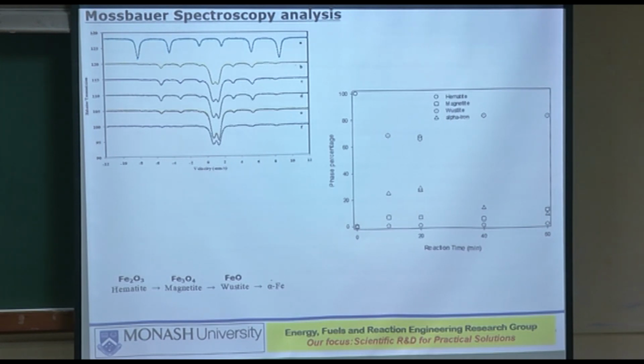You determine, and the codes are in here. This one is for hematite, this one is for Fe3O4 magnetite, this one is for FeO, which is wustite, and this one is for iron 0, alpha iron as we call it. So what we're saying is that this is where you have the Fe2O3, but then after a certain time, these are all done at 900, you start to get the wustite, the metallic iron, and also a little bit of the magnetite.